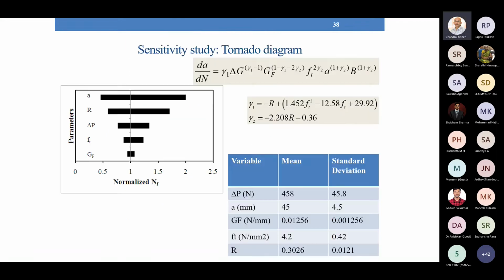And we did a sensitivity study wherein the different parameters involved in this rate of crack propagation are considered as variables, and through the mean and standard deviation, we obtain the tornado diagram and find that the crack length is a very sensitive parameter. So in order to determine the crack length or the number of cycles to failure, the crack length has to be resolved at a very small level. Accurately, we have to obtain that.